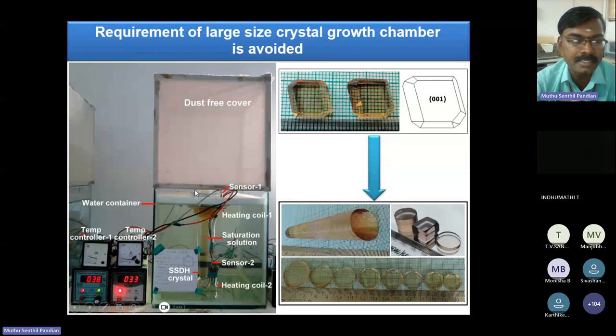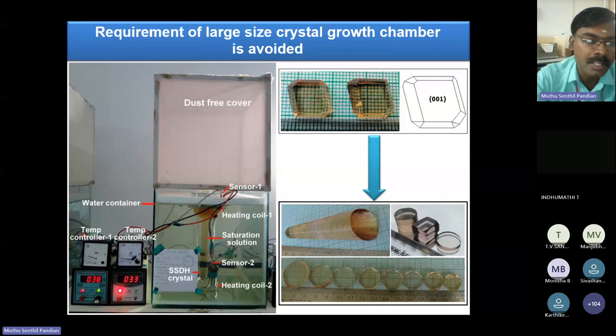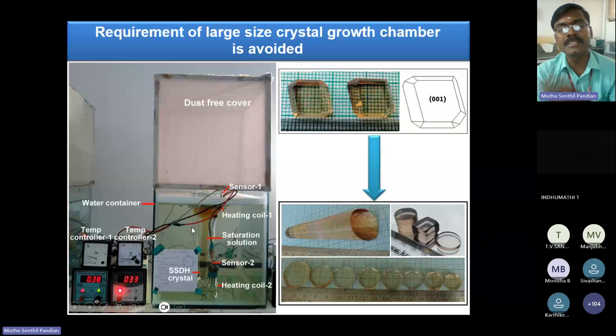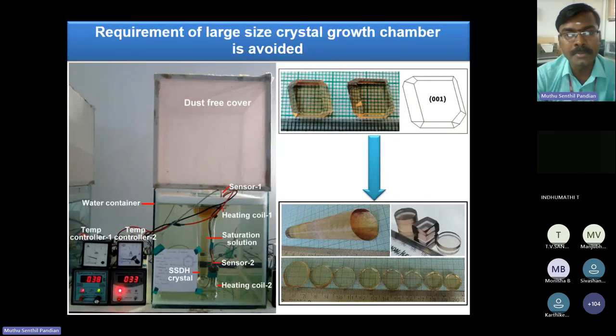So if you construct this SR method in your UG laboratory, PG laboratory, or PhD research laboratory, you need only 5,000 to 6,000 rupees. For constructing this SR method, you need only this 1 feet cross 1 feet water bath. This water bath is nothing but a normal fish tank. And then one glass ampoule and two Kanthal wires, one at the top portion and another at the bottom portion. Two RTD temperature controllers with a sensor, and two ammeters and two transformers. So within 5,000 to 6,000 rupees, one can easily construct this SR method in your laboratory.